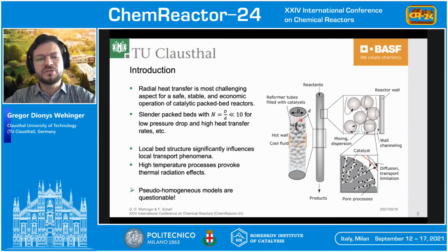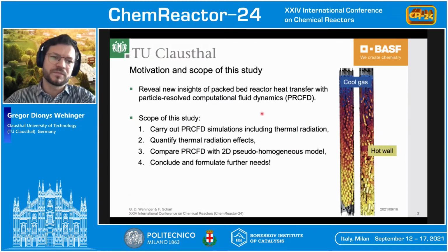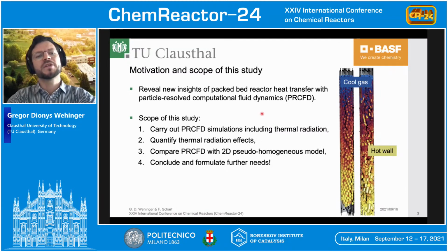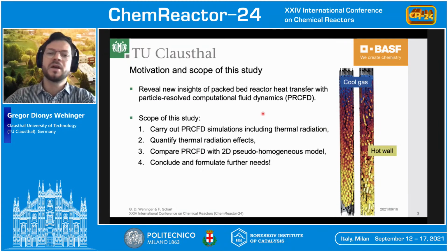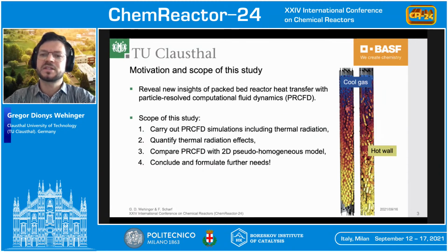So the pseudo-homogeneous models that are mostly used in the design phase are rather questionable. In this study, we wanted to reveal new insights into packed bed reactor heat transfer, without chemical reaction this time, with the so-called particle-resolved computational fluid dynamics approach, PRCFD. In this very detailed modeling approach, we resolve each and every pellet inside a reactor tube and model the gas phase around the particles, as well as, in this case, only heat transfer through the solid pellet.